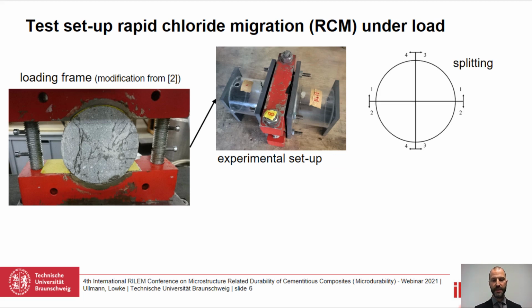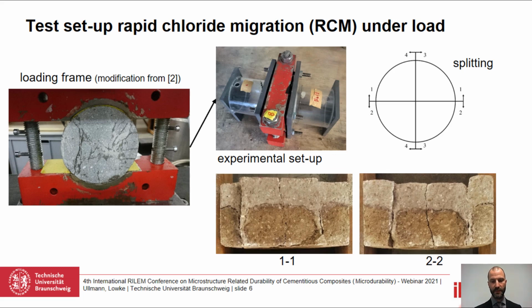And after the test it was important that we took care about the directions of splitting. So as we marked here, we had 4 different directions. We made quarters out of the specimen, and that was due to the appearance of the cracks, as we see on the left side. The main cracks, which were some macro and also micro cracks, more important the micro cracks at the lower load levels, they appeared vertically, and that is why the directions 1 and 2 were the ones that we analyzed afterwards.